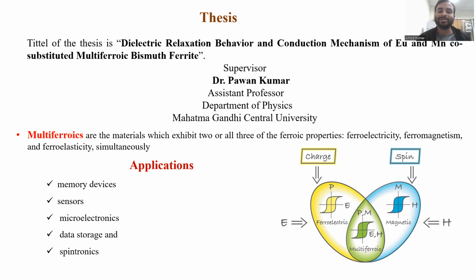Why this? After doping Eu, it increased the dielectric constant and dielectric behavior of bismuth ferrite. And Mn, when I substitute at the Fe site, decreased the oxygen vacancy. So these two enhance the property of dielectric constant. Actually, I want to say this, so I doped it at 1.5%, and let's describe further.